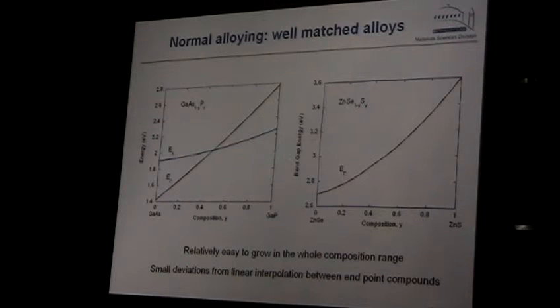As you know, semiconductor materials have this interesting property that you can mix them. If you mix them, you change the properties from one to the other. And the best way is, of course, to change it continuously. So here, for example, you have gallium arsenide with energy gap 1.4 electron volt, and you can replace some of the arsenic with phosphorus, producing gallium arsenide phosphide, a mixed crystal. The band gap nicely goes up to the phosphorus direct gap. At some point, an indirect gap comes out. But the linear approximation is quite good here. There is some deviation, but it is small.